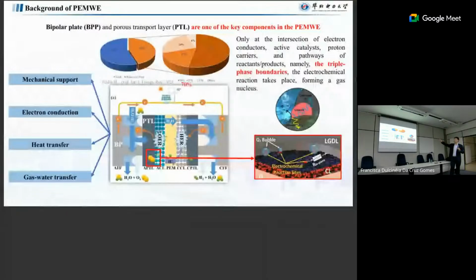Then we can reduce the cost of the balance of the plant. For the PEMWE, we do the same. But if before we had a smaller one, we didn't have a real problem for the two-phase flow transport. But today, if we make it very big, then we have unevenly distributed current, then unevenly distributed heat, then unevenly distributed two-phase flow. We create a lot of problems. We come up with hot spots, and it has influence on the lifetime of the PEM systems.